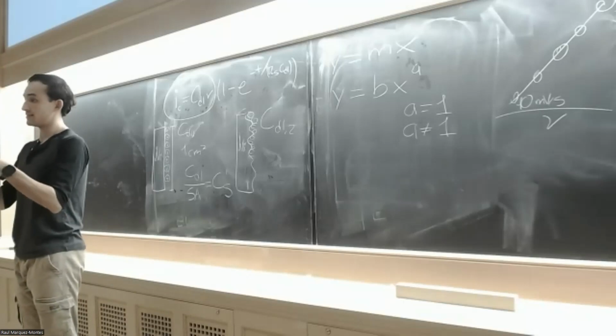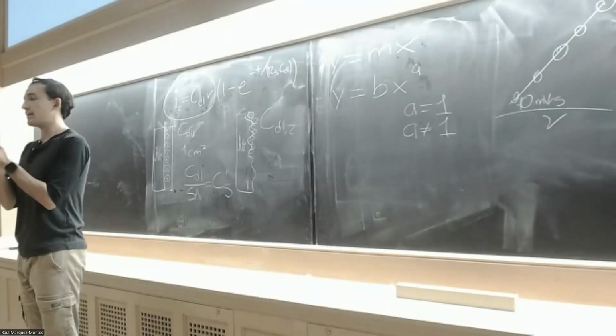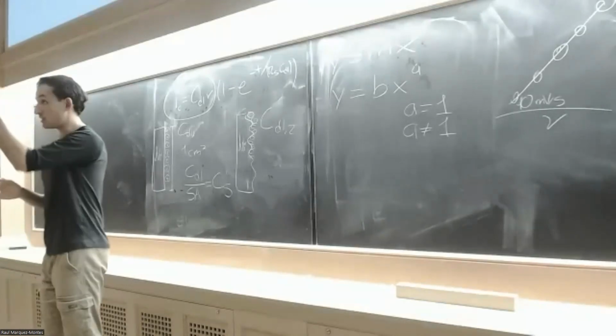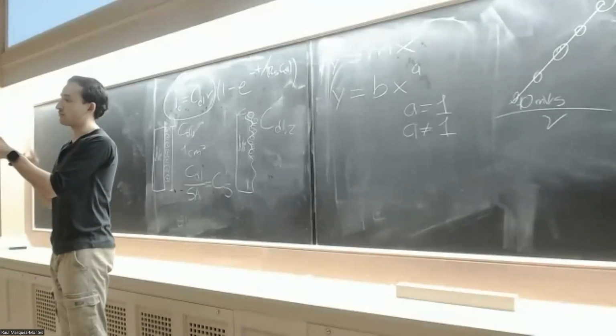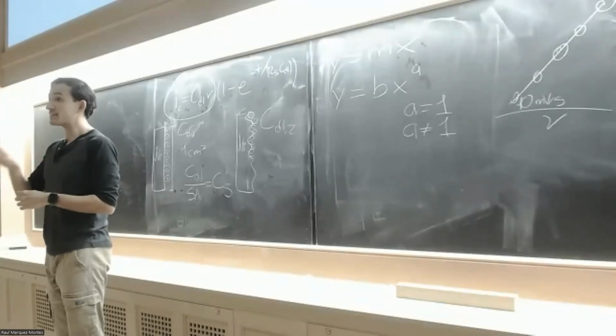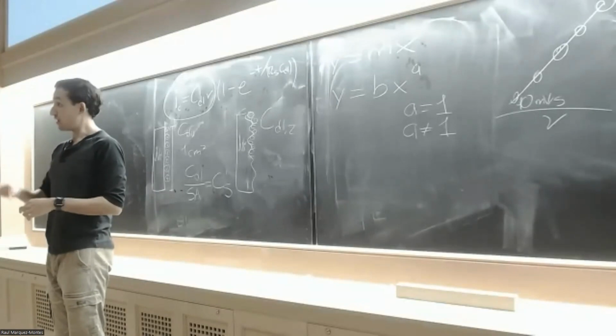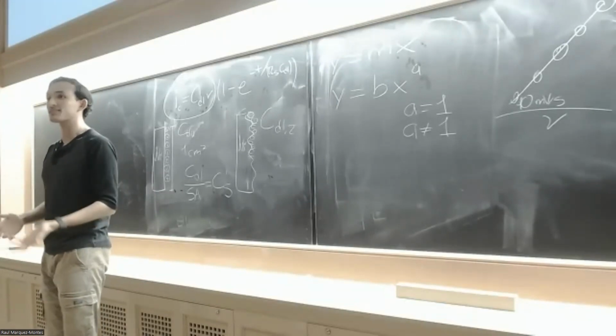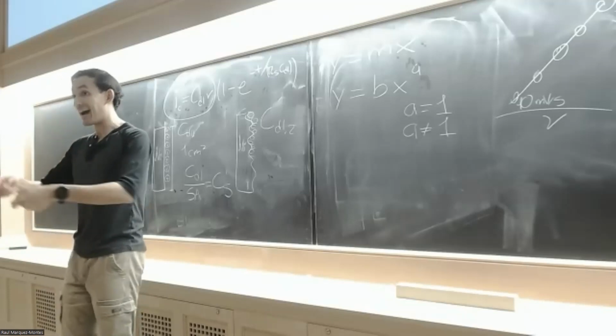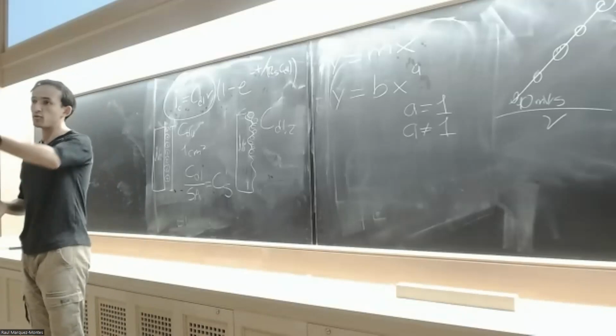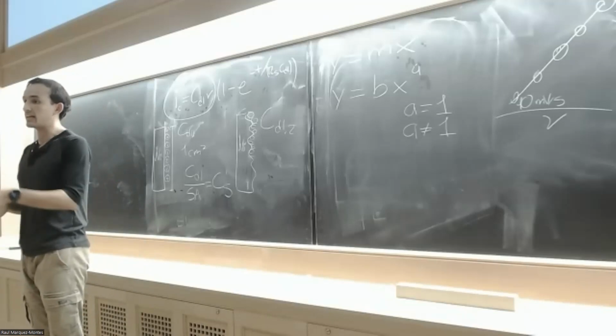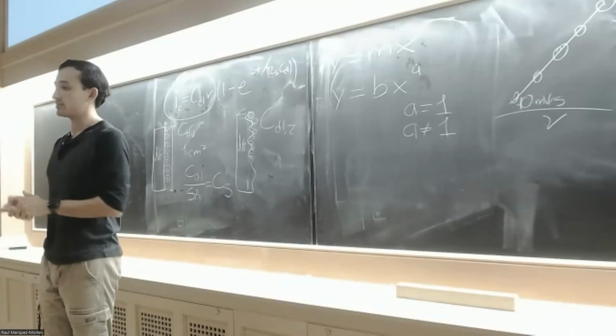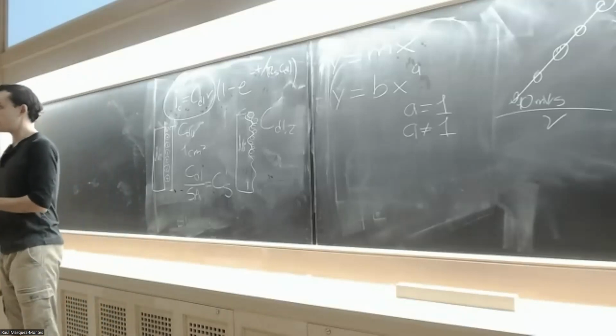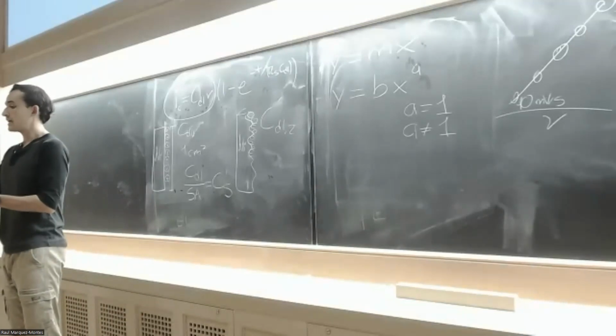going across the system. So that potential, if you wait enough time until your system reaches the equilibrium, that value should be located around the non-Faradaic region, because there's no spontaneous reaction. Notice that it only applies for non-spontaneous processes. So that doesn't apply for batteries, right? Unless you test the material outside the conditions where you do it, like if you grab the lithium cobalt oxide and then you put it in another system with another counter electrode. So using the open circuit potential is a way to find the equilibrium potential, and around that equilibrium is where no reaction happens. So you can use that.